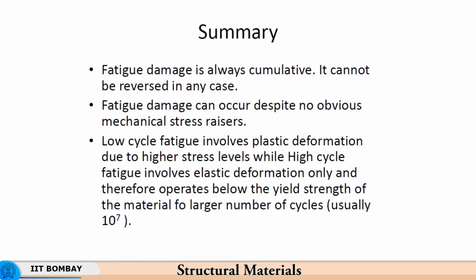So, now with the accumulated fatigue damage, with the ductility getting exhausted with every fatigue cycle, a crack will be nucleated and finally it will propagate. So, there will be a decrease in the stiffness of the product, because now as the crack propagates inwards, the damage is being done progressively. There will be continuous decrease in the stiffness of the product. Low cycle fatigue involves plastic deformation due to the higher stress levels, while high cycle fatigue involves elastic deformation only.